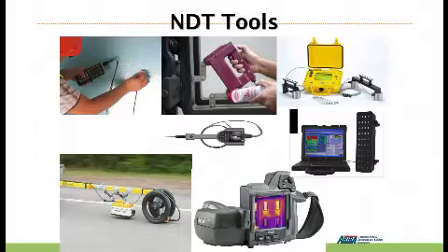Or your chloride is far deeper, even beyond the steel, so you have to use a different type of preservation treatment. And you have the magnetic particle testing that identifies cracks, and you have the infrared camera that identifies the difference in the temperature between one location and the other. How is that helpful? The locations where you have concrete damage are going to be warmer than the locations where you have no damage.